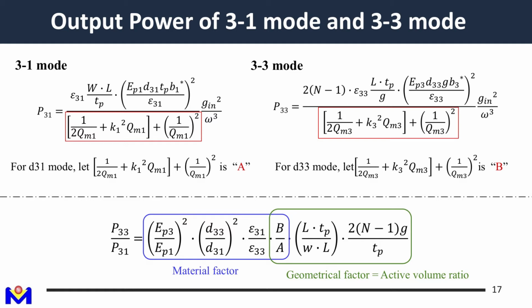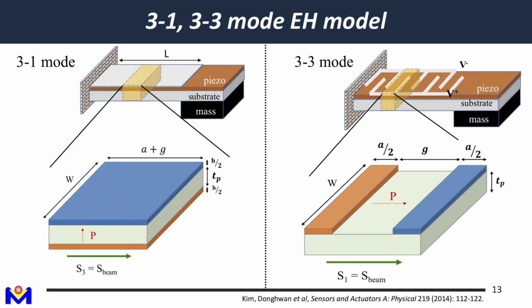And for geometry factors, the most important factors we have here are G and TP. And G and TP, when we go back to the drawing here, TP is actually the thickness of the piezoelectric film, and G is actually the gap between the interdigit electrodes of 3-3 mode.